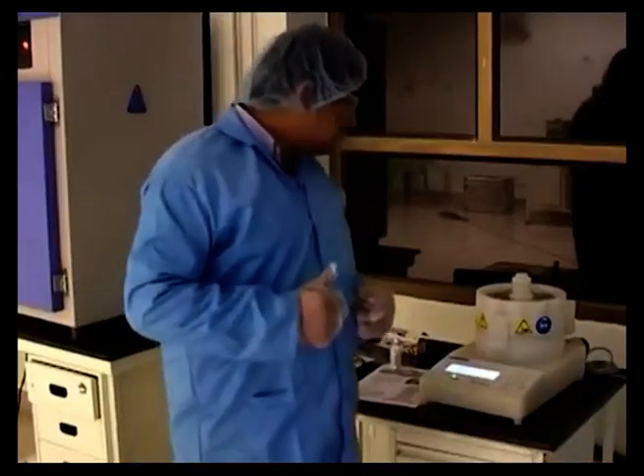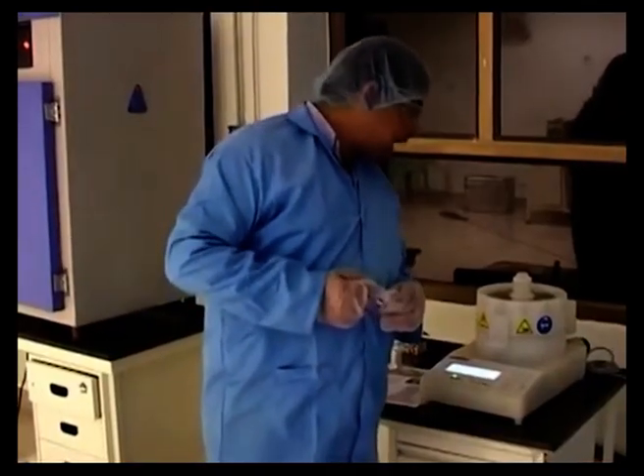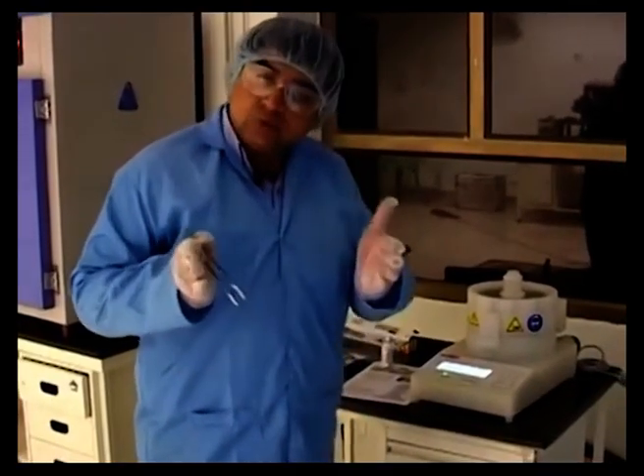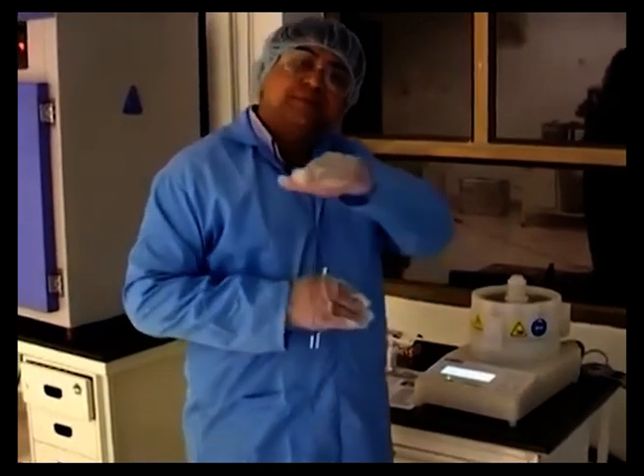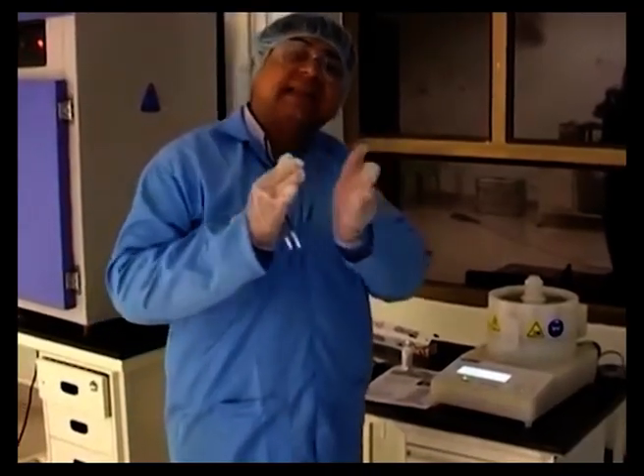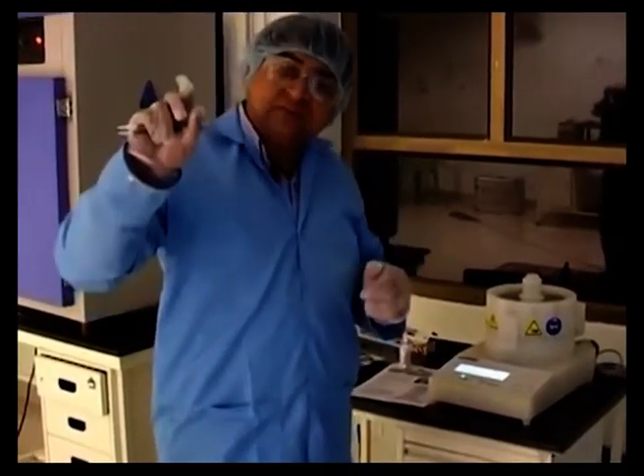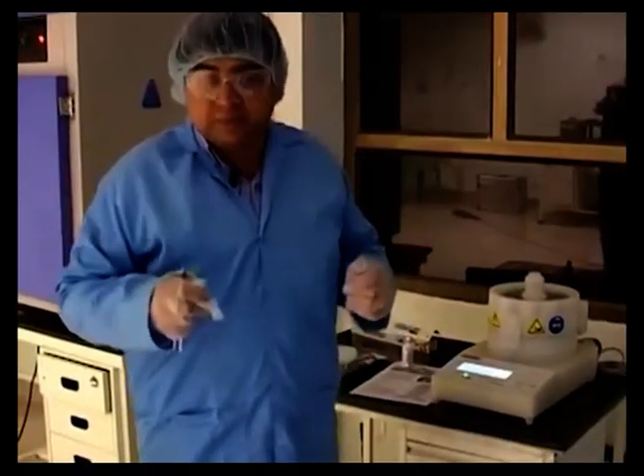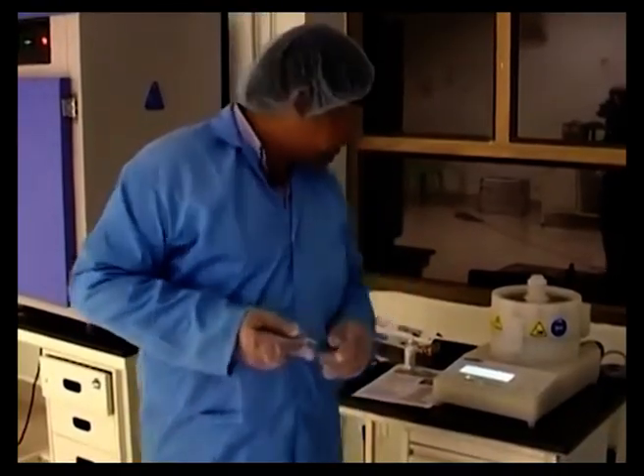Also, we need to assert one basic fact, that the table that we are using for keeping or aligning our hot plate should be perfectly parallel to the ground, because otherwise there may be a possibility of the resist running to one side, thus creating a thicker film at one end, which is highly undesirable, because we want uniformity in the film thickness, which also determines the sizes and nature of our structures and features.